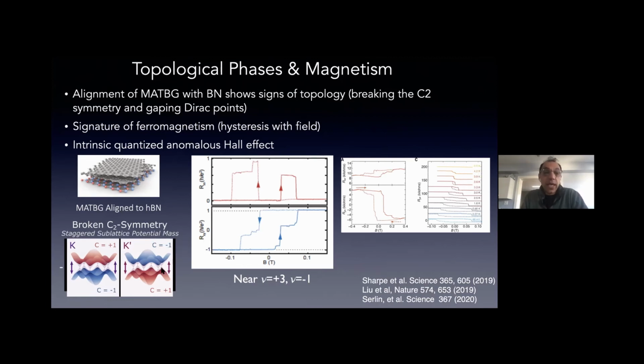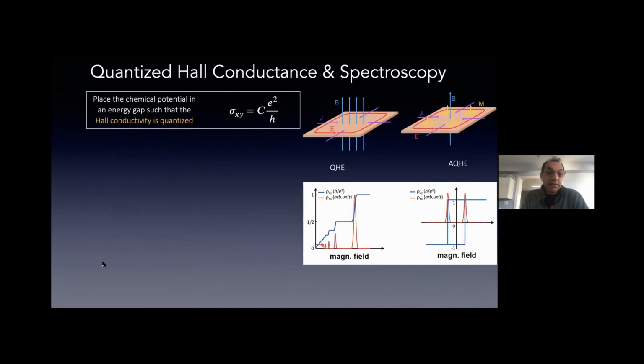And it turns out, as Dimitri explained, this is related to the Dirac physics of the band structure of this system. You can think about the alignment with the boron nitride breaking the sublattice symmetry of the graphene lattice and opening up a gap at the Dirac point. And opening up this gap basically exposes the fact that what you started with, because it's graphene, has this Berry curvature, and from occupying this subband structure of these flat bands, you can create Chern insulating phases. So this looked very exciting to us, and we were trying to make devices that were actually aligned to search for these effects. But we found that we didn't even need to do that. Correlations allowed us to see signatures of the Chern insulating phases.